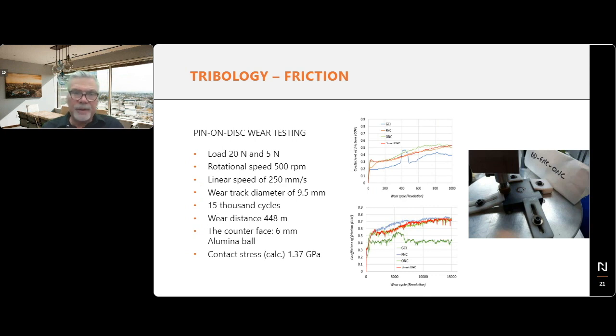Now, this is an interesting study because it shows friction. Here, at first, you try to interpret this. Of course, the blue line, in case you cannot make out the colors on your monitor, the blue line, which is at the bottom of the top diagram, is just pure gray cast iron. And this gray cast iron appears to have a bump in the middle, but probably it has been caused by accumulation of wear material and should not be really relevant to the study.